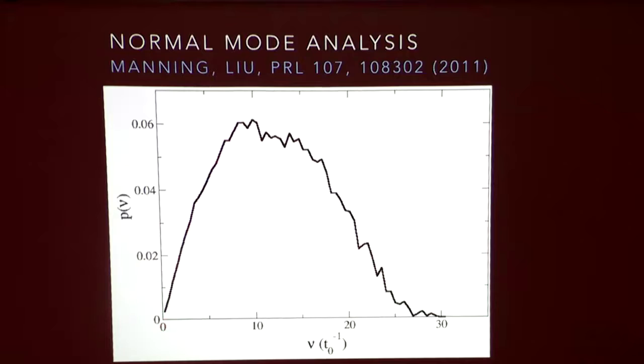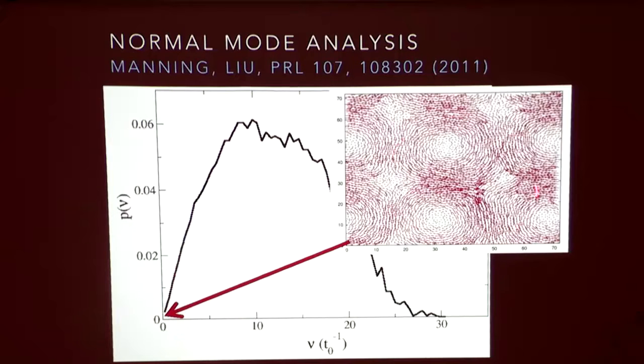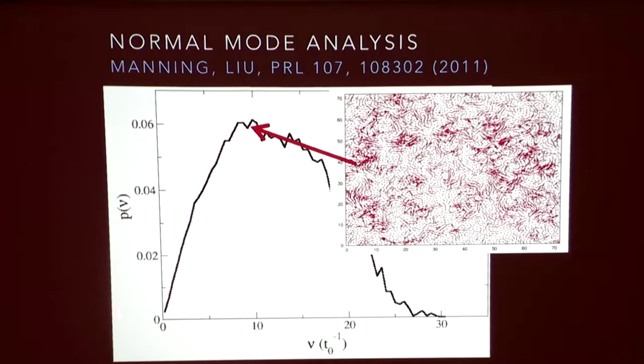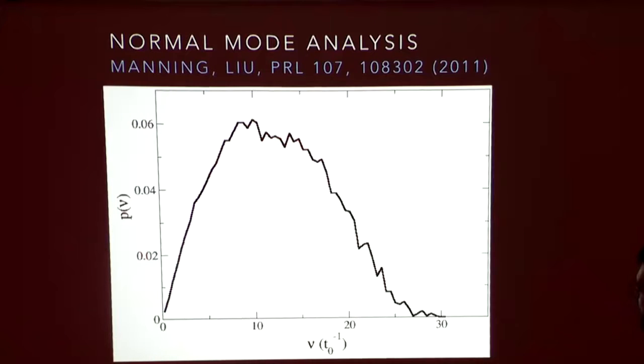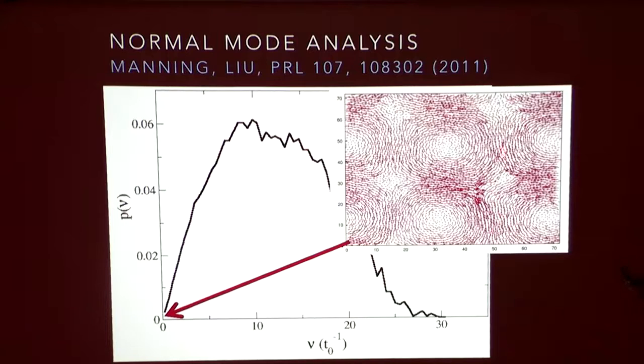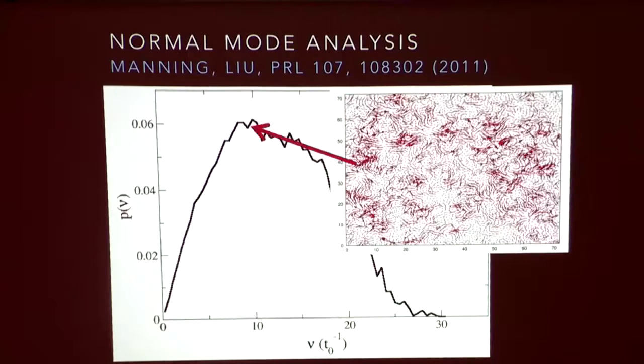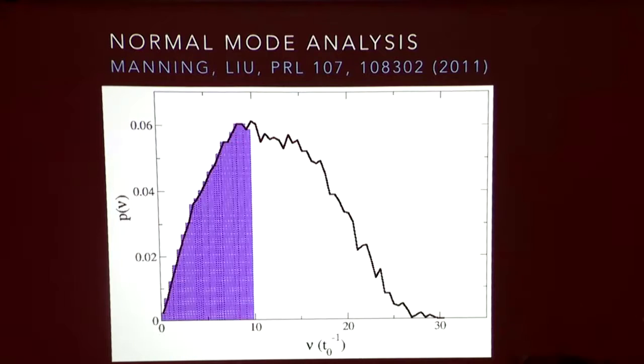Down at low frequency, you have plane wave modes dominating, and as you go up you get more disordered modes. But in the amorphous material, these plane wave modes are not pure, they're admixed with whatever the plane waves are. There are some regions that seem to be undergoing slightly more deformation, a little floppier or softer than the surrounding medium. So what they decided to do was look at these modes below the boson peak, look at the eigenvectors, and pull out the atoms that disproportionately move in the eigenvectors for these low frequency modes.